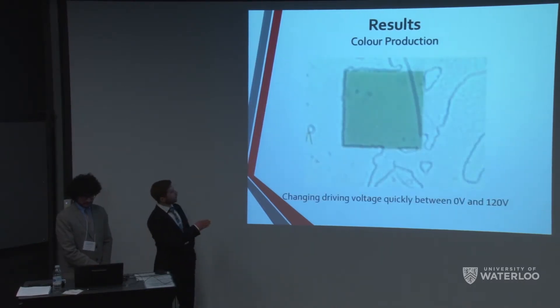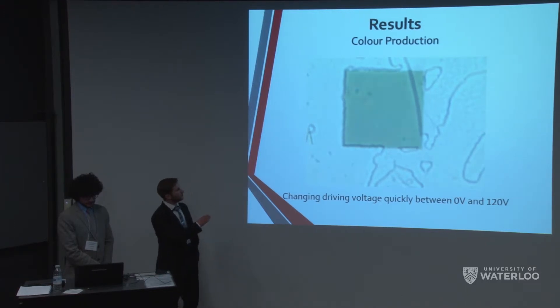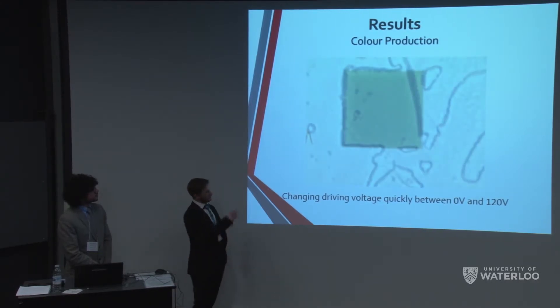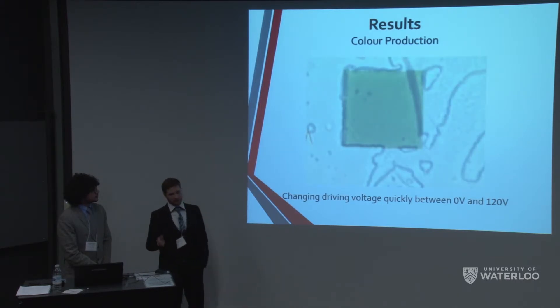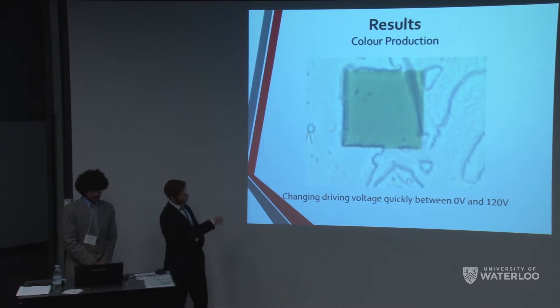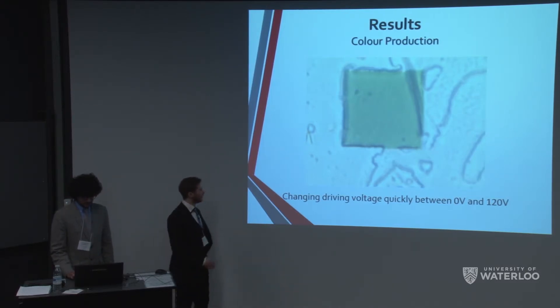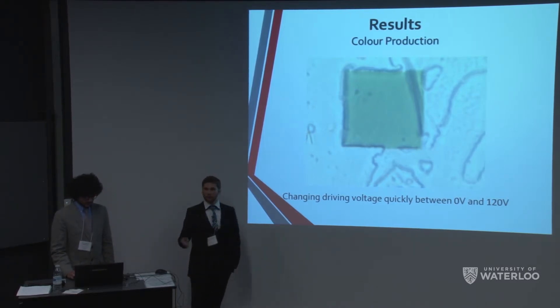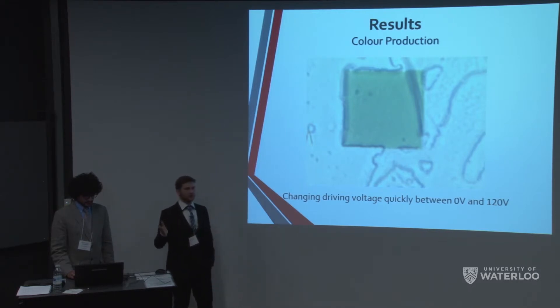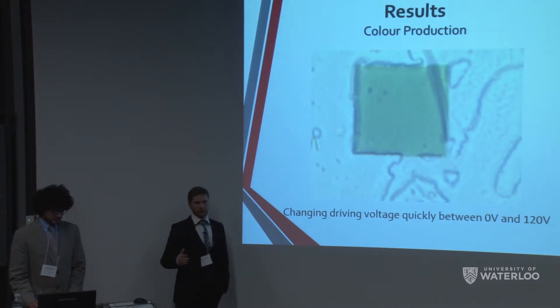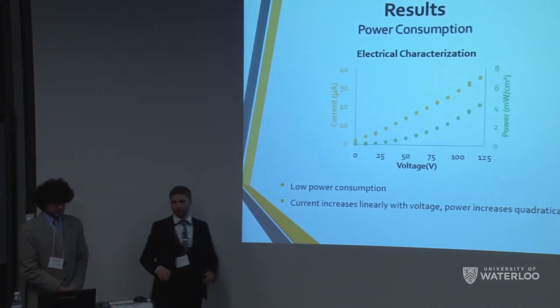Here's a video of the color change. It starts off green with no voltage, and then at 100 volts it's more of a tan color. At lower voltages you can see a lot of grain boundaries because the liquid crystals align themselves to the surrounding topology of the gold and ITO. But once we apply a sufficiently large voltage — approximately 20 volts — the electric field is strong enough to reorient them into a single orientation.